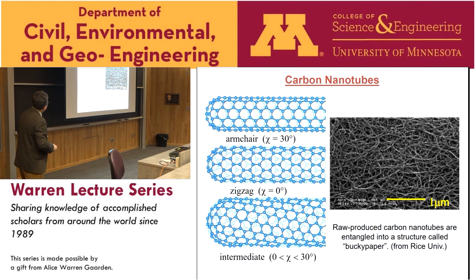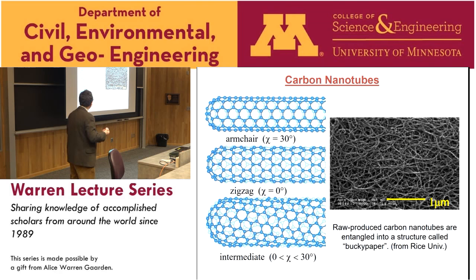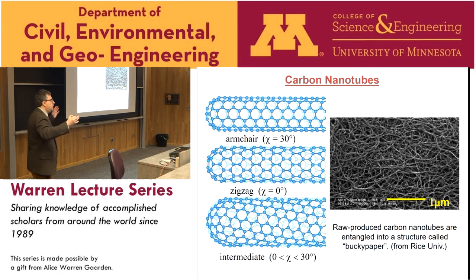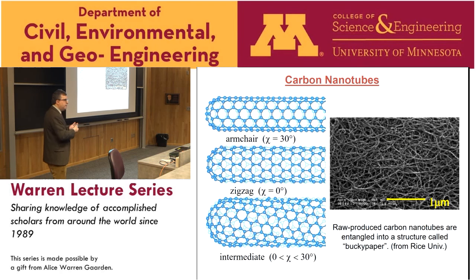What you see here is an entangled structure called Bucky paper. We have single-wall carbon nanotubes that are entangled and bent. Surprisingly, they look like cooked spaghetti instead of uncooked spaghetti, considering the fact that they are very strong and stiff structures. The reason for this bending deformation is that they do bend because of long-range van der Waals interactions with each other, which drive the organization of this mat into bundles. So tubes are organized in bundles, and they also bend — we have strain energy and van der Waals energy stored there.